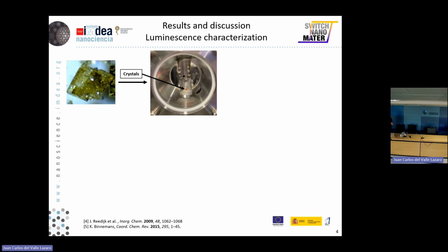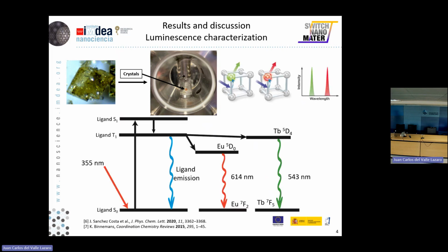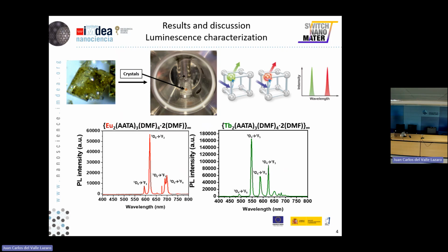Once the material was completely structurally characterized, we proceeded with the luminescence characterization. For this purpose, we dried the crystal, put it in the sample holder, and introduced it in a hermetic chamber where we put all the gases inside with a stream of inert gas. After that, we excited the sample with a 355 nanometer laser, obtaining the excitation of the antenna ligand, and with an intersystem crossing from the excited triplet state of the ligand, we produce the luminescence of the europium and the terbium, obtaining a similar spectrum to the one shown before with the 614 nanometer maximum of the europium and the 543 nanometer maximum of the terbium.